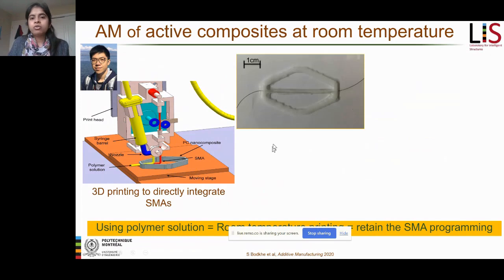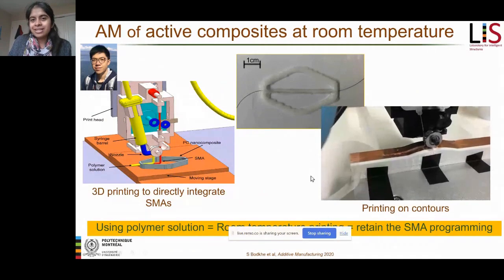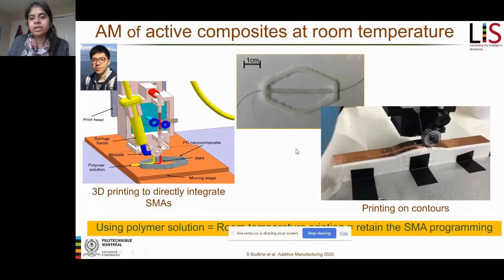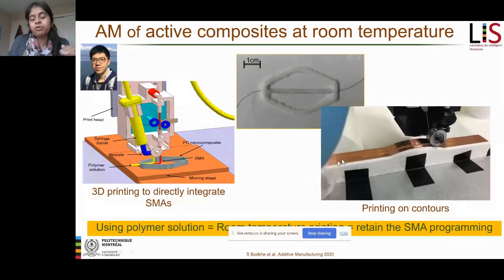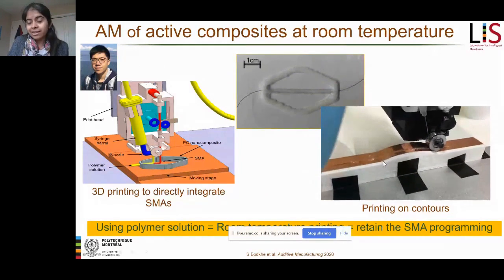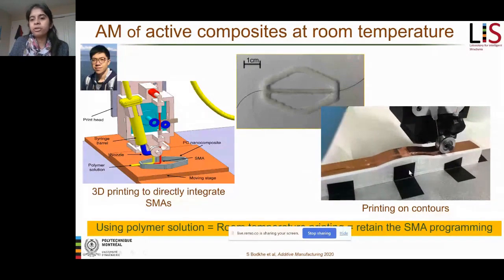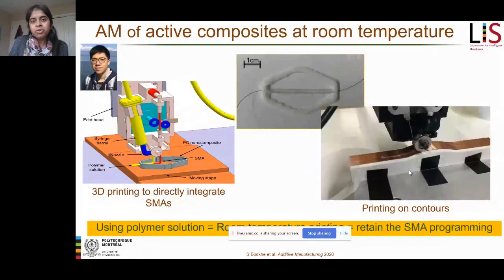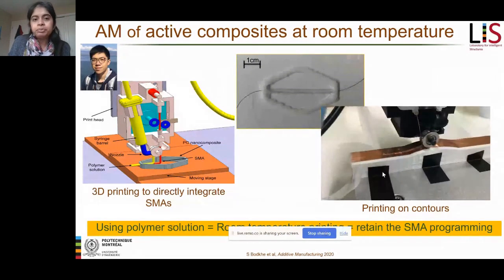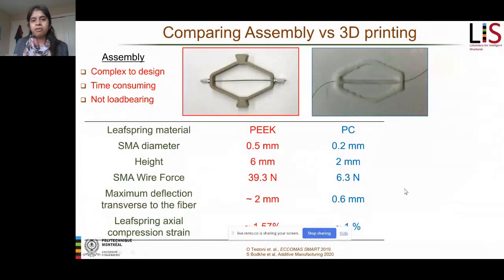And here is one of the leaf springs, and there is an SMA that is integrated into it. The interesting part is that now we're not restricted to in-planar structures, but we can also go out of plane and create conformal structures. So that really increases our design freedom. This was something that we were looking for. In comparison to the assembled PEEK and SMA structures, here we had to go with polycarbonate because we could not dissolve PEEK.